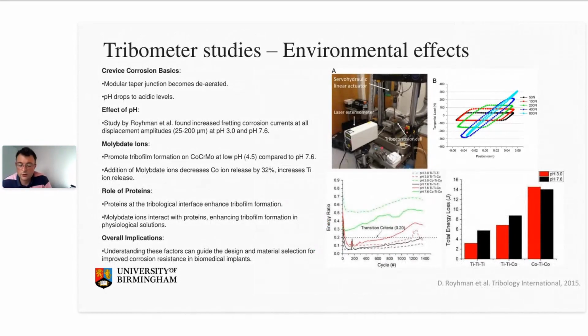And similarly, environment is being studied. We know from a crevice corrosion point of view that the local regions within a crevice will become deaerated and will reduce in pH. Some work by researchers at Rush, from Markus Wimmer's group with Alfons Fischer, has really paid attention to these tribochemical effects within these fretting corrosion contacts. And as expected, a decrease in the pH can affect the total energy loss and ultimately the total wear.